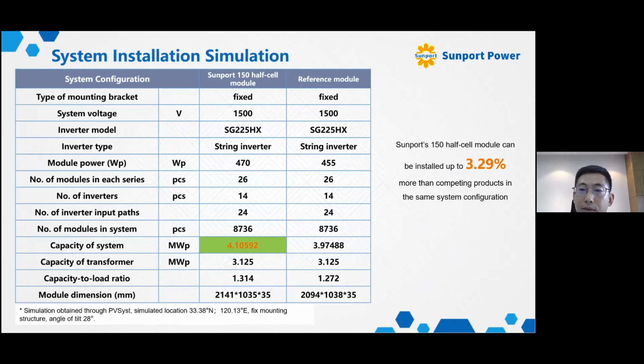And here we have a 166 size single crystal wafer based MWT module and the reference ordinary module. These two modules have very similar dimensions, you can see here. And the MWT module has higher power, which is 470 watts compared to 455 watts. For this ground project, we use exactly the same system design, same inverter, same number of modules. From the table here, we know that you will have 3.29% more system capacity, which is 4.1 megawatts in total, by using the MWT half cell product compared to the regular module.